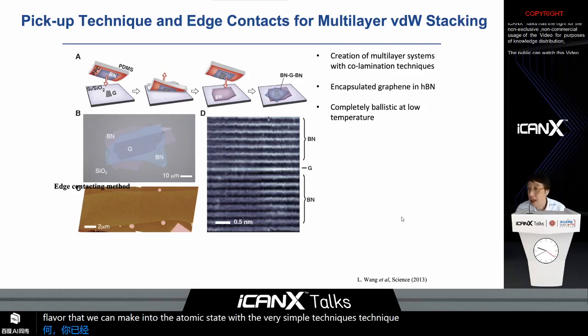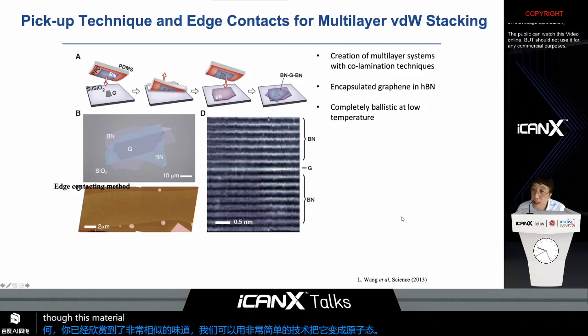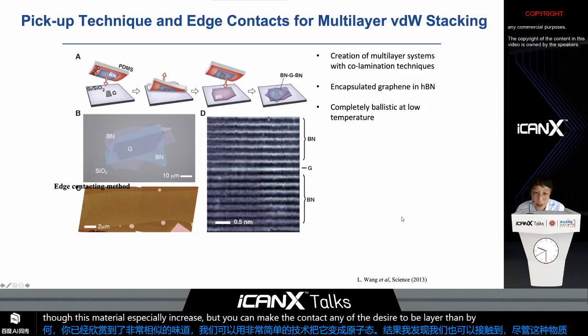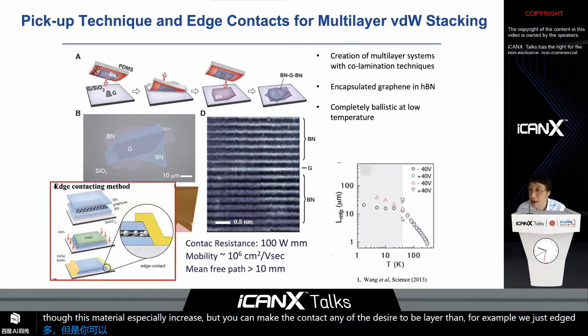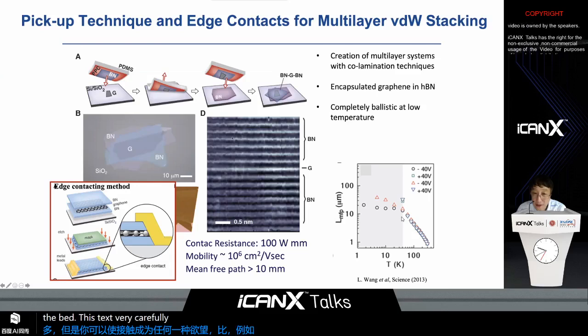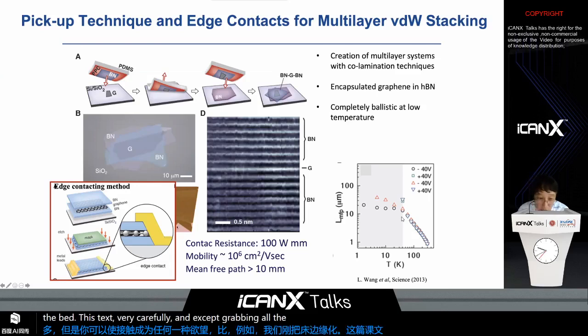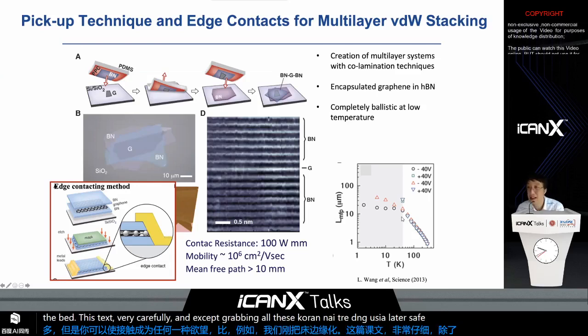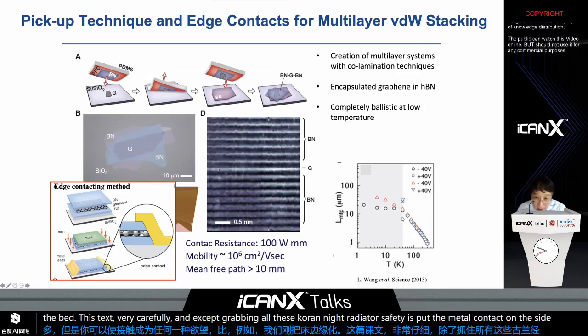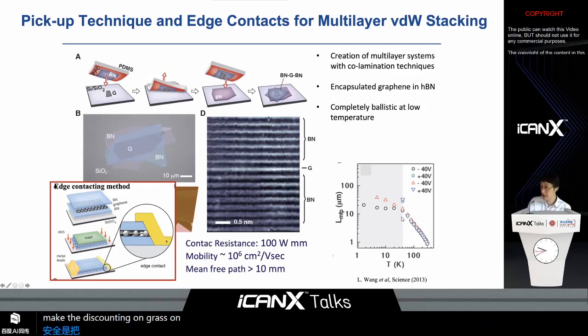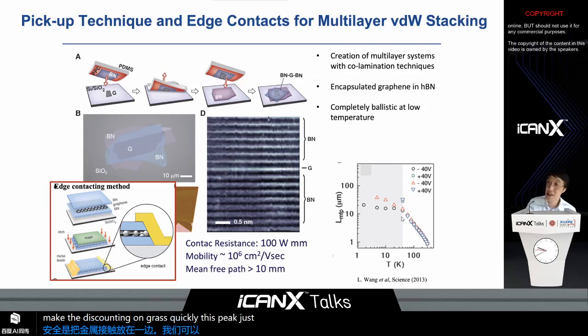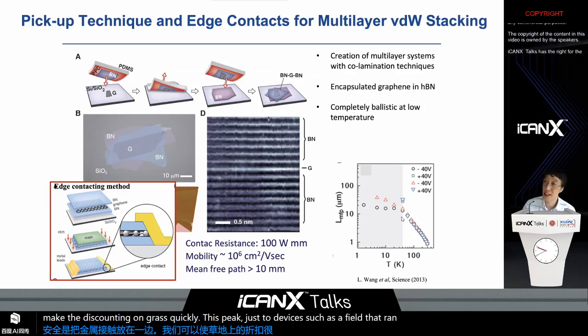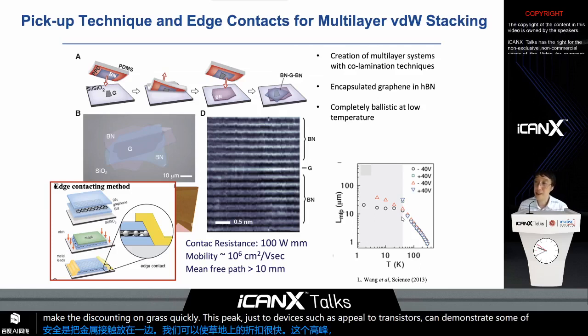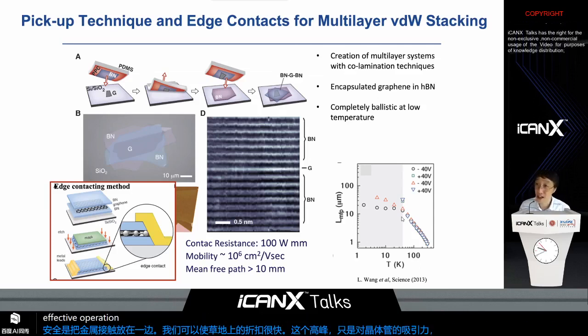It turns out we can also make contacts onto these materials. In principle, you can make contact to any of these atomic layers at will, right? For example, we just etch this stack very carefully, exposing the graphene and the boron nitride insulator. If you just put the metal contact on the side, we can make contact to graphene, and quickly this becomes a device such as a field effect transistor, so we can demonstrate some simple field effect operation as a transistor out of it, right?